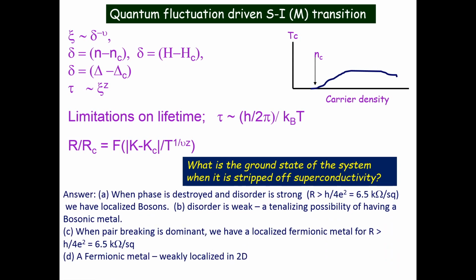Now the fundamental question to ask here is, if the system is stripped of superconductivity, what is left behind? The answer is, when the phase is destroyed and the disorder is sufficiently strong, that means the sheet resistance is more than the quantum 6.5 kilo ohm per square, we have the so-called localized boson. That's what is called the dirty boson picture of a superconductor-insulator phase transition. If the disorder is weak, then we have this tantalizing possibility of having a bosonic metal.